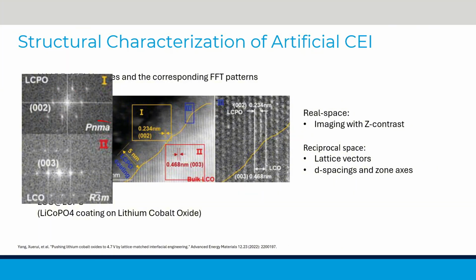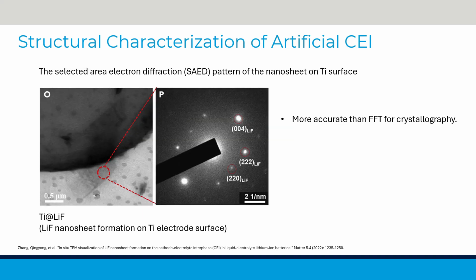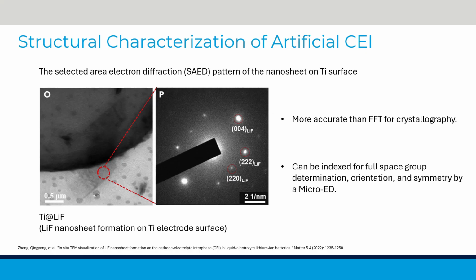In this example, the Pnma space group indicates that the LCPO adopts an orthorhombic structure. To obtain more precise crystallographic information, selected area electron diffraction can be performed on the particle surface if the feature size permits. This technique provides a direct experimental measurement of electron scattering in reciprocal space. When carried out using micro-ED with a sample tilt holder, the reflections can be indexed for full space group determination, orientation, and symmetry.